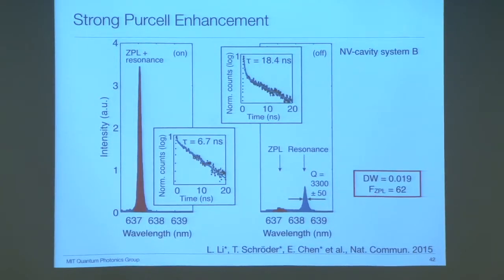The original Debye-Waller factor is about 1.9%, and the Purcell factor enhancement is over 60. And with this high-resolution grating, it only has a spectral range of about 50 nanometers. We are not able to see the overall view of both the NV ZPL and the phonon sideband. So we switch to a lower resolution.